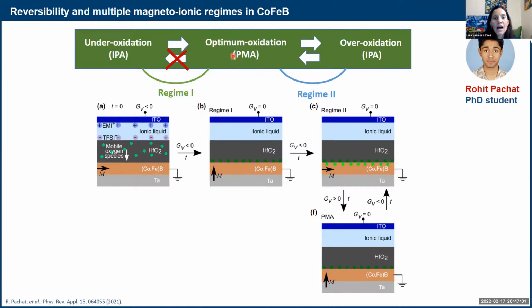So once we get to PMA, we probably start adding more oxygen, and this oxygen needs to go somewhere. It's probably going to go to secondary binding sites or interstitial sites, or maybe a little bit more into the layer. And this is the part that we think is reversible. So as you can see here, the dark green dots at the beginning, and then the light dots coming later, could be moved back and forth.